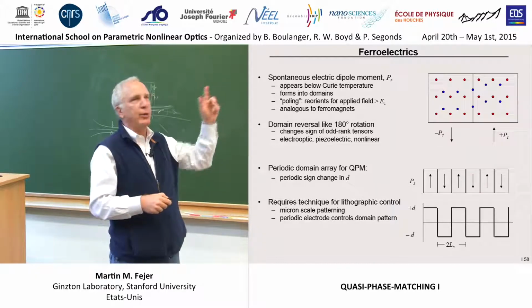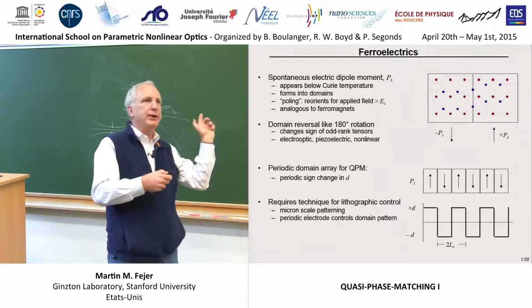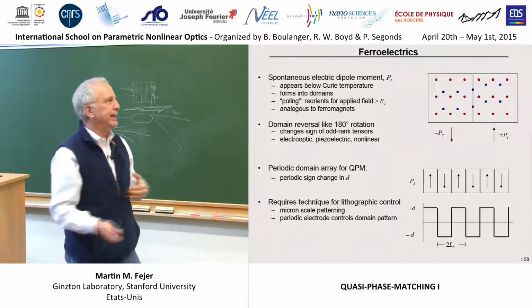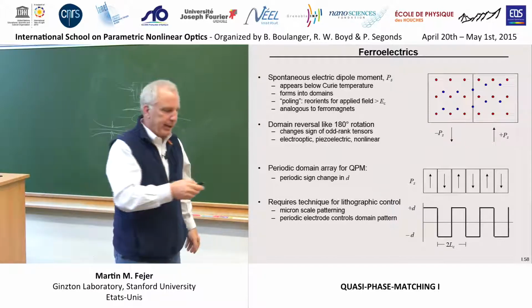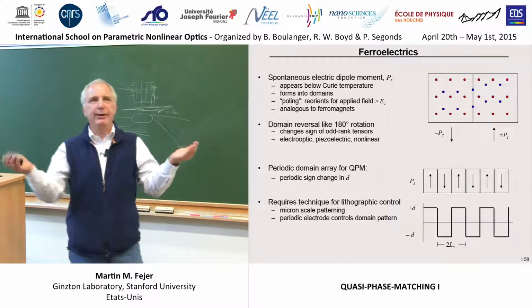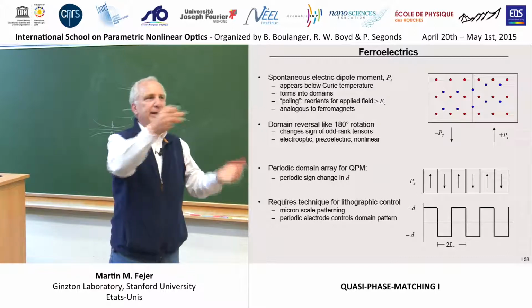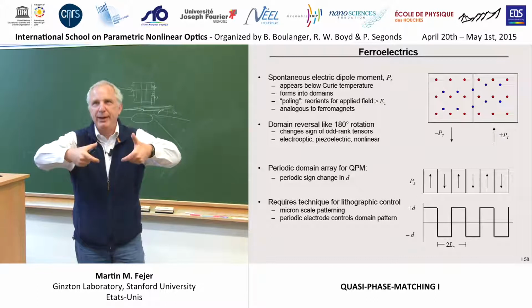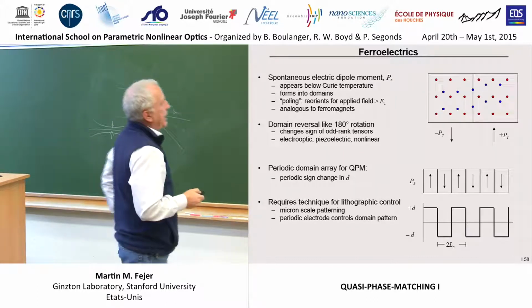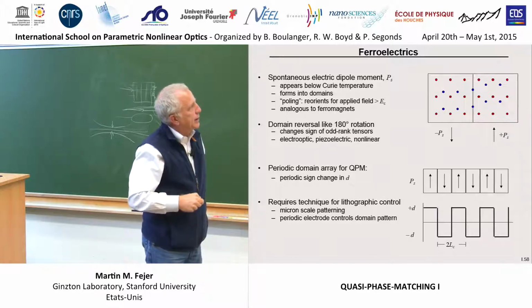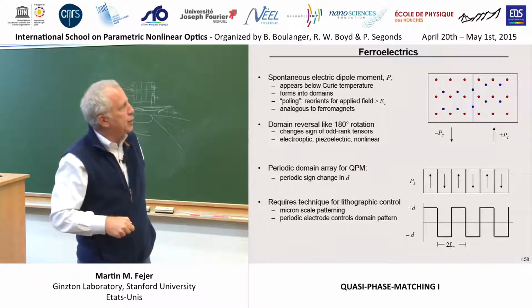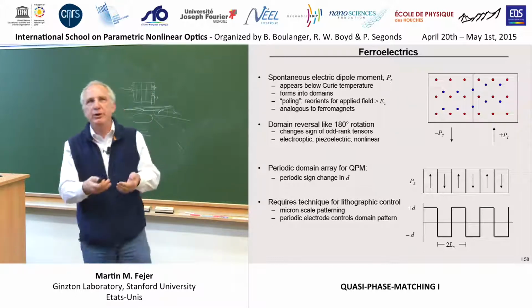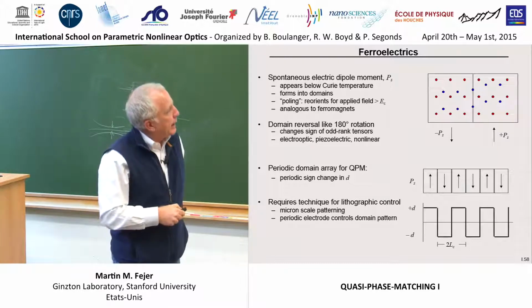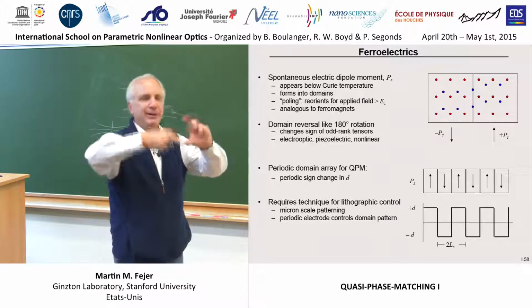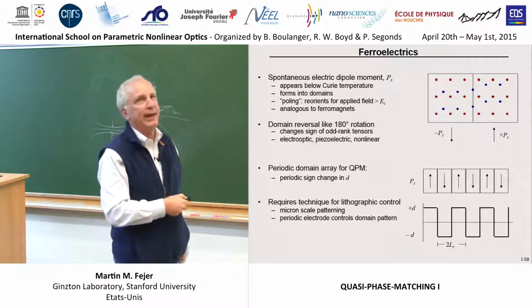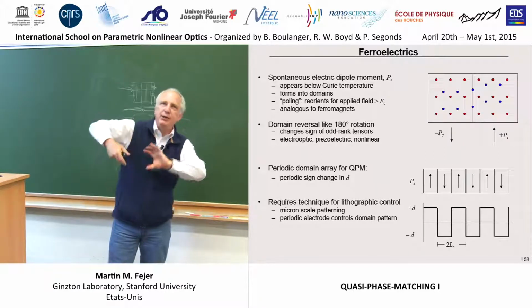And that's conceptually pretty similar to unit cells that contain spins. If the spins are all aligned one way on one side of a wall and the other way on the other side of a wall, that's a magnetic dipole domain that's up or down, right, with a domain wall separating it. You can flip magnetic domains by applying a magnetic field to them. You can flip electric dipole moment domains by applying electric fields, because the energy of a dipole aligned with an electric field is opposite to the energy when it's misaligned, right? So you can try to make the dipoles align with the electric field. In addition to having this spontaneous electric dipole moment, an up and a down domain, if you think about this, Benoit was talking about centers of inversion, inversion symmetry. Well, you've basically flipped the crystal structure. If you rotated this 180 degrees, it would look like that one.